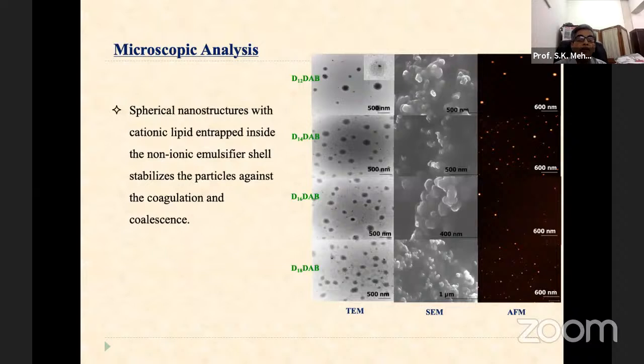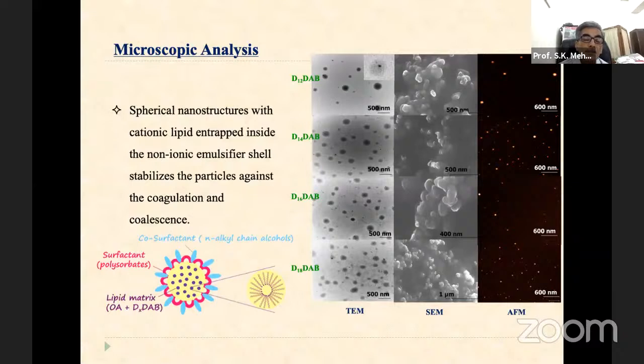So spherical nanoparticles, as you can see, with cationic lipid trapped inside the non-ionic emulsifier shell, which stabilizes the particles against coagulation and coalescence. You can see the particle size, and SEM and AFM, all these measurements were done. And this is the proposed structure which we have. We have the lipid matrix inside, and surfactant is coated outside along with the co-surfactant. And along with that you have OA, oleic acid, and DDAB inside as the lipid matrix. So it is stabilized by surfactant, that is, Tween we are using, and also the alcohols which we are using, that's the co-surfactant.